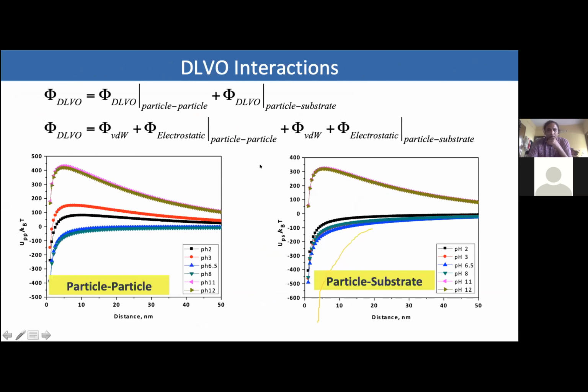So I talked about colloidal interactions. In an evaporating drop problem, one has to account for both the particle-particle interaction as well as the particle-substrate interactions. And because we are dealing with charged particles, we'll have DLVO interactions for both. That means we will take the contribution of van der Waals forces and electrostatic forces both for the particle-particle system